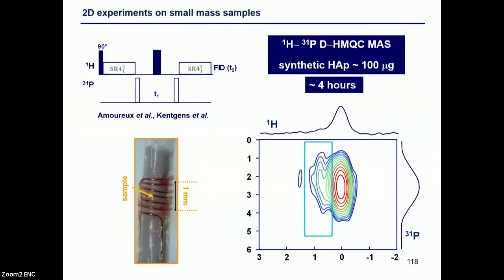Just an example to prove that it works: in 4 hours we were able to record a complete D-HMQC experiment, which is highly robust, to correlate, for instance, proton and phosphorus. Here the detection was on the proton side. We used a particular recoupling scheme, but you can use other ones in order to improve the sensitivity of your experiment. And by playing with the recoupling time, we were even able to show some correlations which were, I would say, unexpected, and we are still trying to understand them.